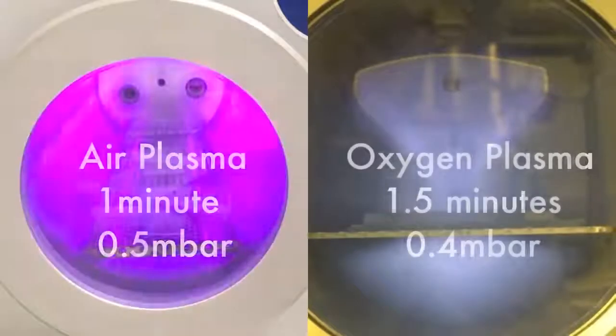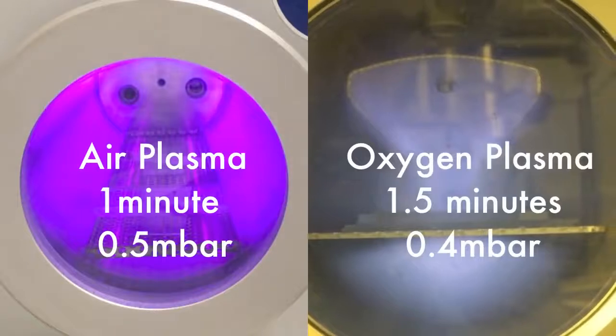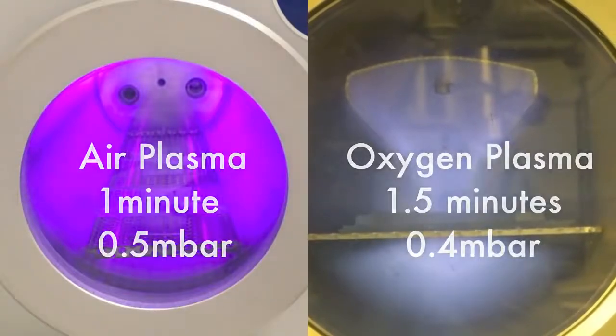We used oxygen plasma treatment for 1.5 minutes at a pressure of 0.4 millibar. You can use other gases such as air for treatment, but the parameters may change. The surface treatment effects last for approximately 10 seconds, so you must work quickly for the next step.